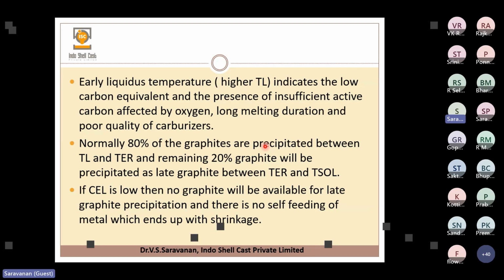Once it is hypereutectic, graphite starts precipitating first at this particular point. 80% of the graphite precipitates between TL and TER. What is TER? I will tell you later. The remaining 20% forms between TER and T solid. T solid means after completion of the solidification. How much graphite precipitates between TL and TER, and how much between TER and T solid, determines the quality of the casting.